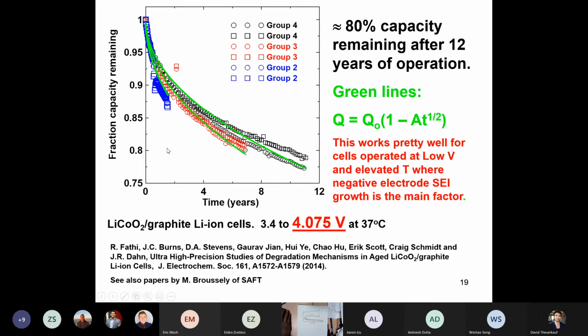There's cells that have been running for, you can see, 11 years here. 11 years. That's a long time. And these green curves are what you would predict for this capacity loss with this very simple model. And it's decent. That's the point of this. It's a decent fit to these curves. Now it's very, very likely that the SEI growth is not governed by the t to the 1/2 law exactly.